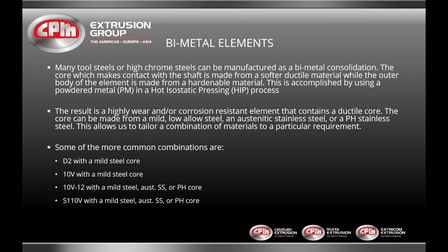The core can be low carbon alloy steel, which is most common, or an austenitic or PH core. Some of the combinations could be D2 or 10V with a mild steel core, 10V12 or S110V with a mild steel, PH, or austenitic stainless steel core.